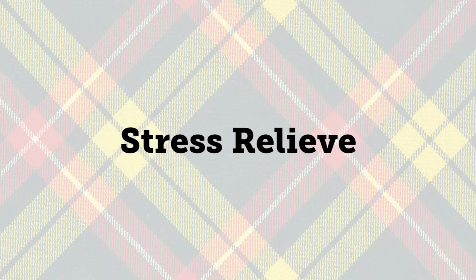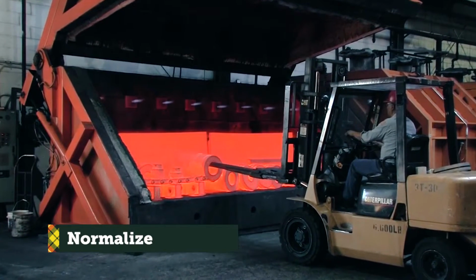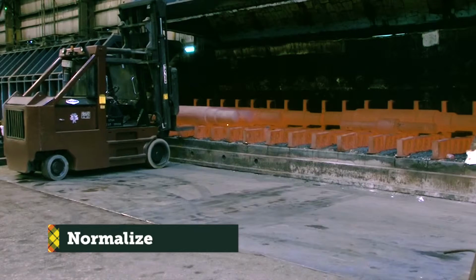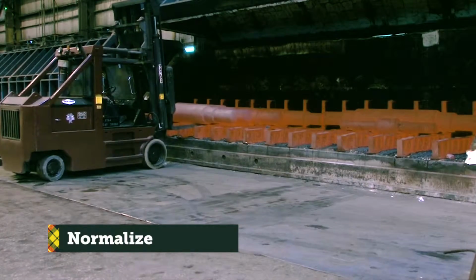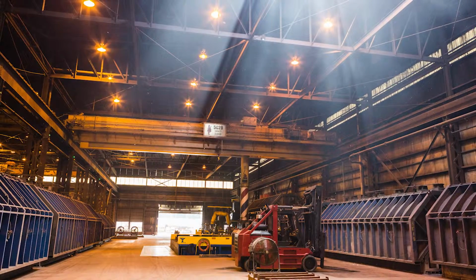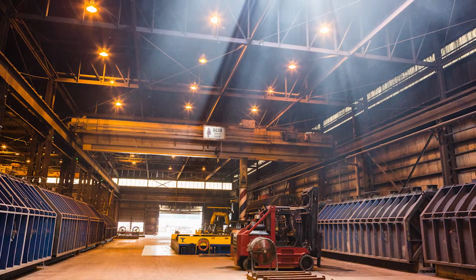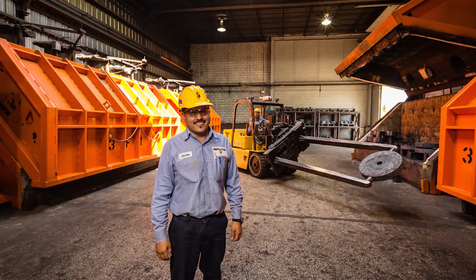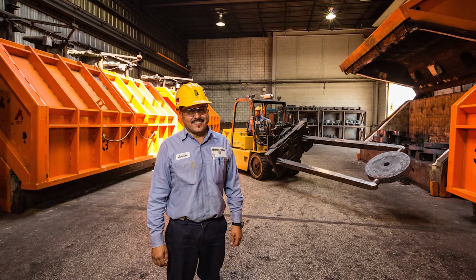Some of the most common heat treatments that we perform here at Scott Forge are normalize, anneal, quench and temper, solution anneal, and stress relieve. Normalize is primarily used to promote uniformity within the piece and get nice even hardness on your forging. This is going to help tremendously with your machinability and help reduce stresses up front. This is also a great way to set up your forging for optimal subsequent heat treat, such as a quench and temper, carburizing, or flame hardening.